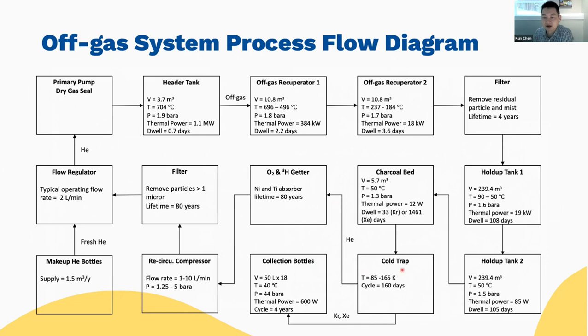I will show you how the cold trap and the collection bottles are working in the future slides, but let's keep going with this route. And it will go to the oxygen and tritium absorber. The purpose of it is, first of all, to remove oxygen and also to remove tritium from the system. We're using a nickel and titanium absorber. I need to point out that because ThorCon 500 is using sodium and beryllium fluoride, we're not using lithium. So the tritium generation from the power plant is actually much less than reactors using lithium. So there's not a significant generation of tritium from the power plant.